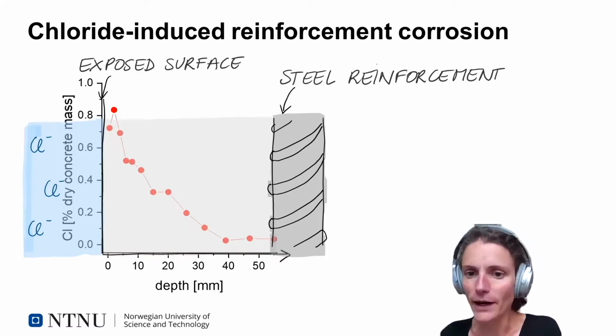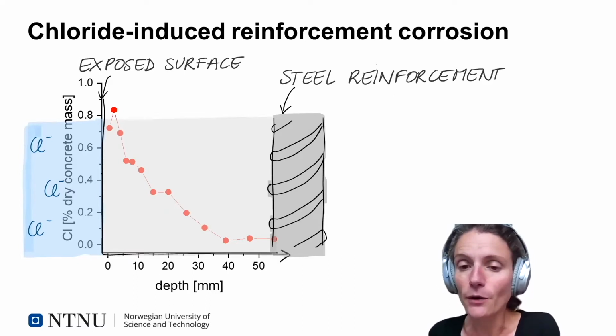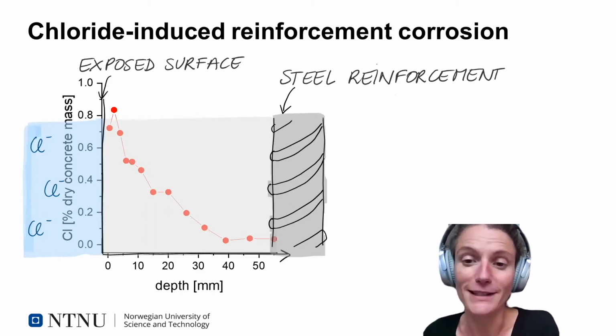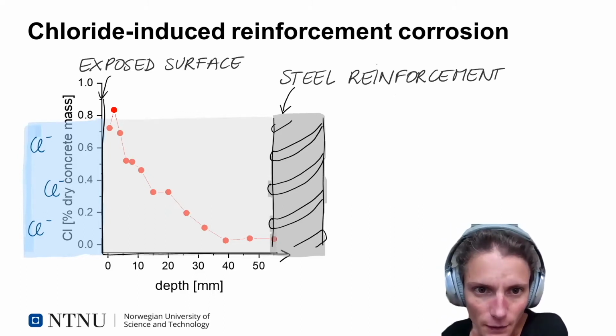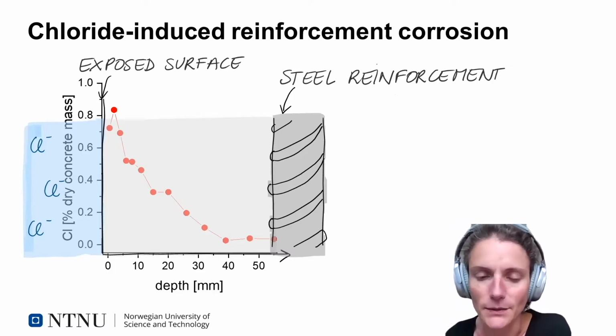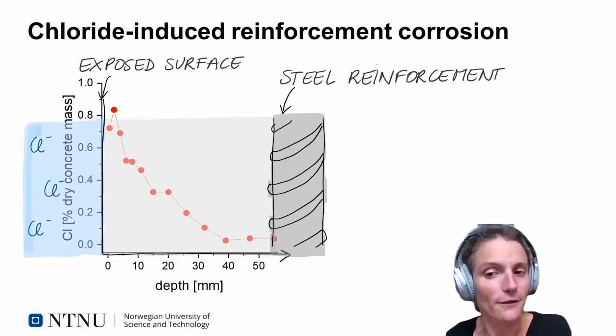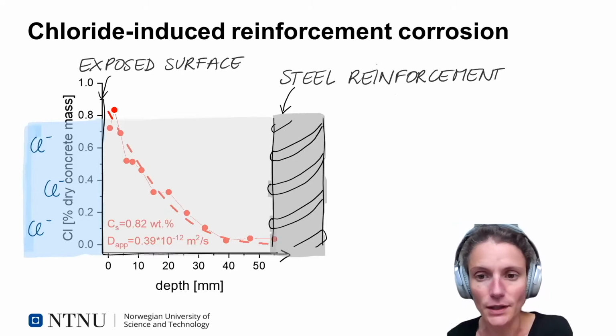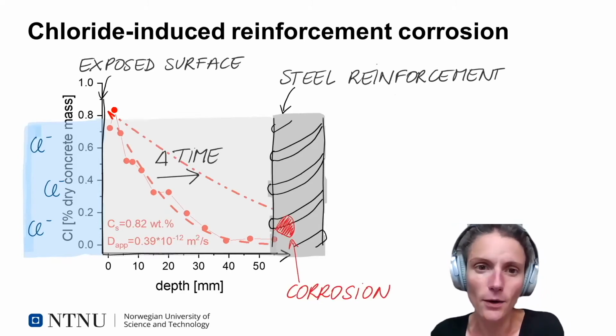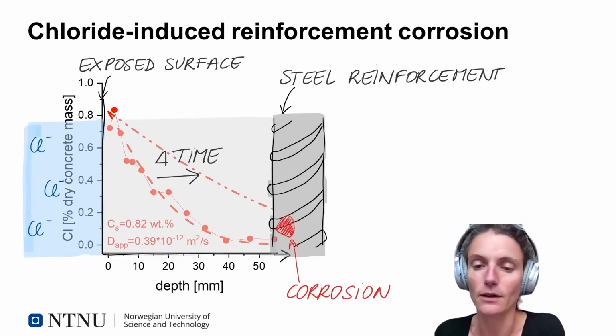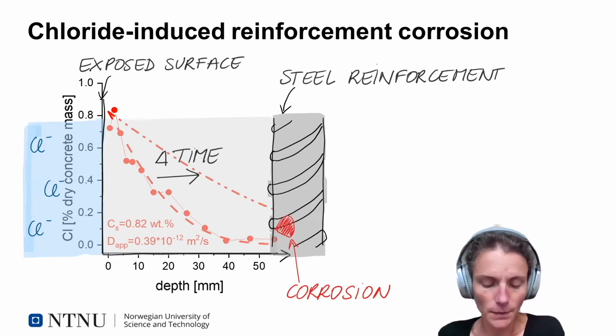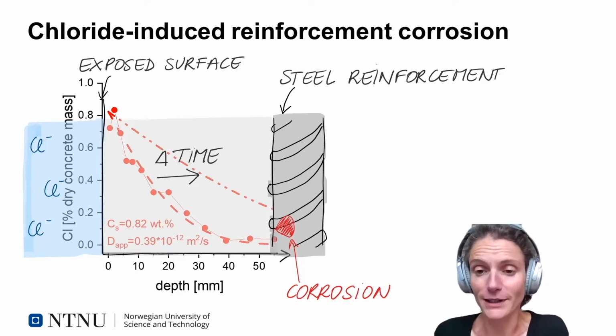This is a chloride profile which I obtained from a concrete which was submerged in seawater for 16 years. And we can see that the chlorides have penetrated the cover and have come as deep as approximately 40 millimeters. You can use these chloride profiles for something else as well. So an engineer can use them to try to predict how long it will take until you have a certain probability for corrosion. And we typically use empirical models for this.